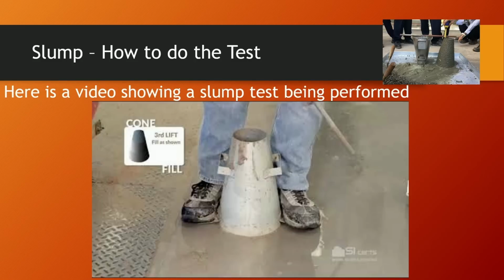Second lift. We'll fill the mold to 2/3 by volume. We'll rod this lift throughout its depth, penetrating the lift below by approximately 1 inch. Third and final lift, we'll completely fill the mold. We'll rod this lift throughout its depth, penetrating the lift below by approximately 1 inch.